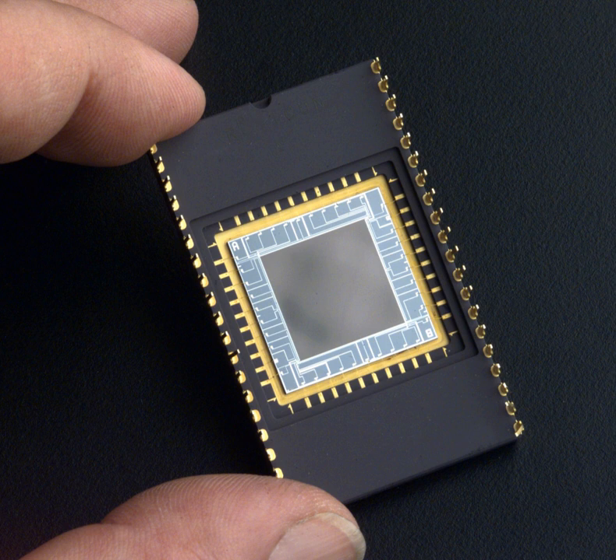Simon Sze details the advantages of a buried channel device. This thin layer, equal to 0.2 to 0.3 micron, is fully depleted and the accumulated photogenerated charge is kept away from the surface. This structure has the advantages of higher transfer efficiency and lower dark current, from reduced surface recombination. The penalty is smaller charge capacity, by a factor of 2 to 3 compared to the surface channel CCD.